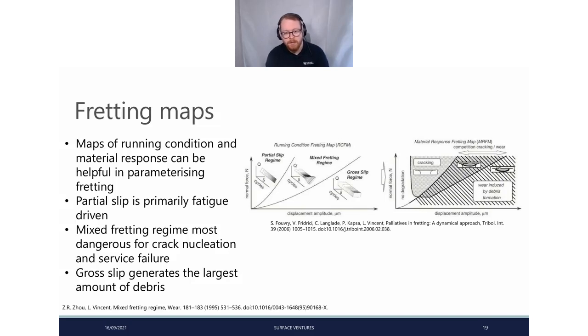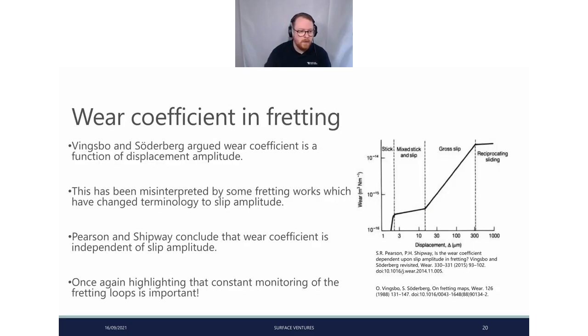Mixed fretting is where we're beginning to generate wear particles, but of course, there is still this fatigue mode there. And then gross slip is very much driven by debris formation. This is where our oxidation comes in. If you have a contact which oxygen can get to, you will oxidize your wear debris, creating hard particles, third body wear, increasing the wear during your fretting process. So something to be aware of.